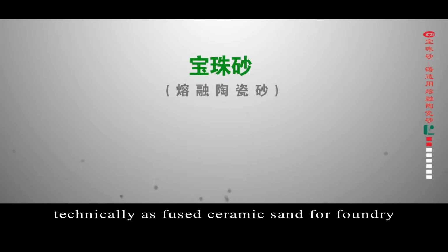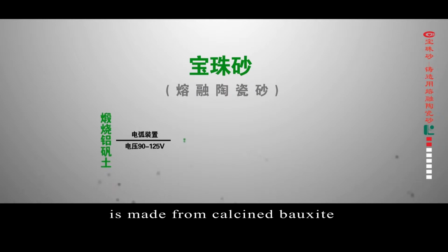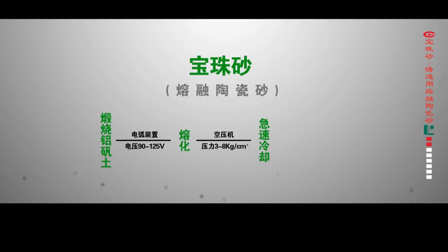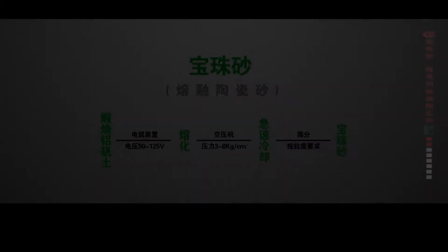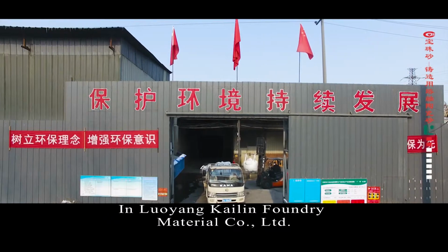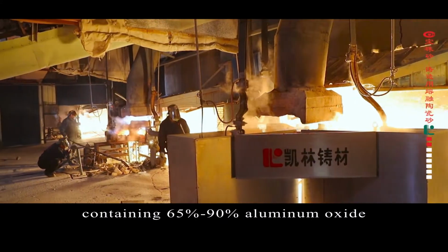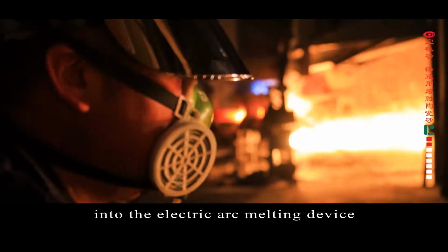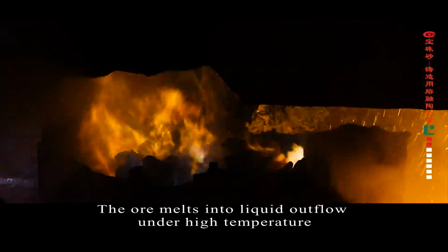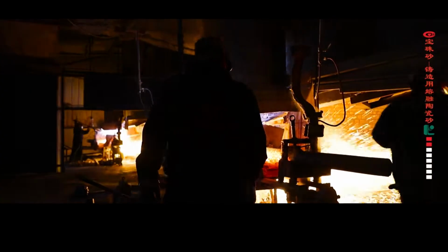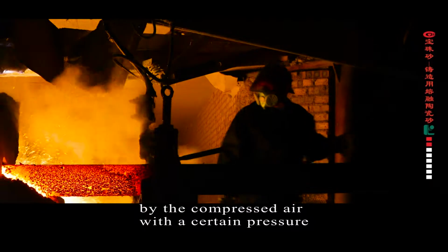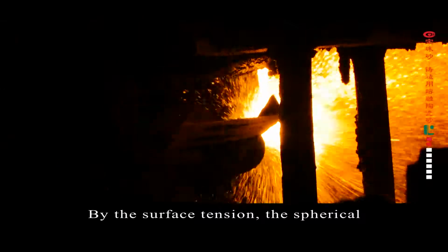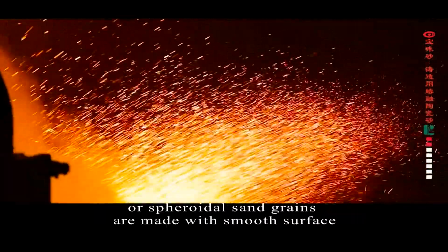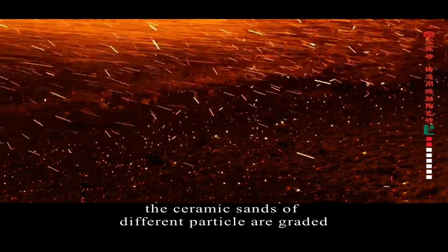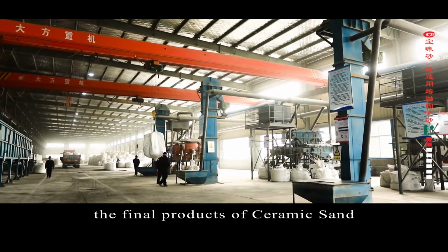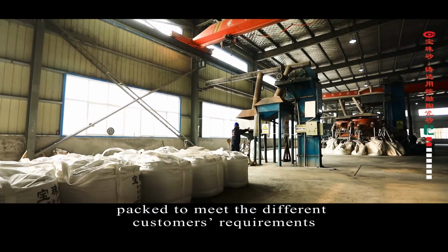Ceramic sand, technically known as fused ceramic sand for foundry, is made from calcined bauxite, whose main content is aluminum oxide, processed by melting, blowing, sieving, and blending. In Luoyang Kailin Foundry Material Company Limited, operators put the calcined bauxite containing 65 to 90% aluminum oxide into the electric arc melting device. The ore melts into liquid outflow under high temperature. At the moment, the outflow is blown into fine particles by compressed air with a certain pressure. By surface tension, spherical or spheroidal sand grains are made with a smooth surface. After cooling and sieving, the ceramic sands of different particle sizes are graded. At last, the final products of ceramic sand are packed to meet the different customers' requirements.